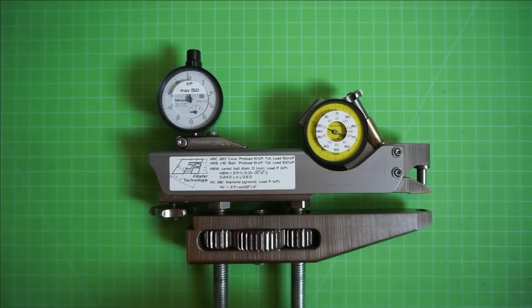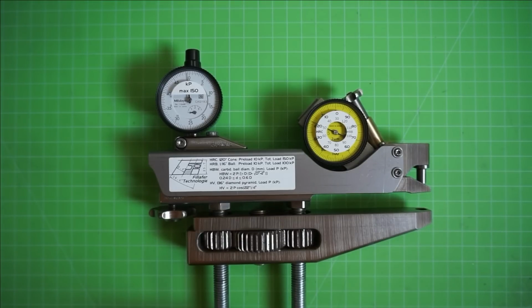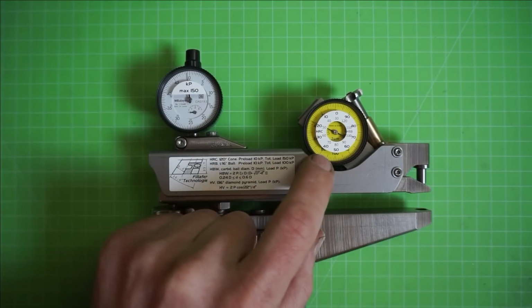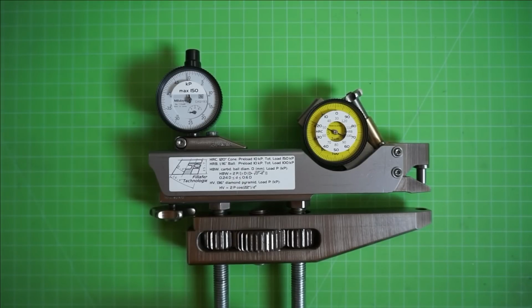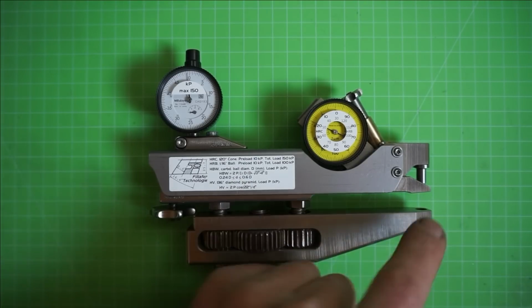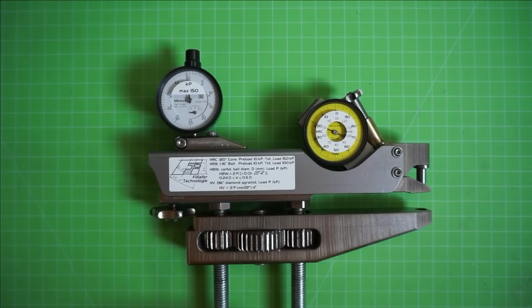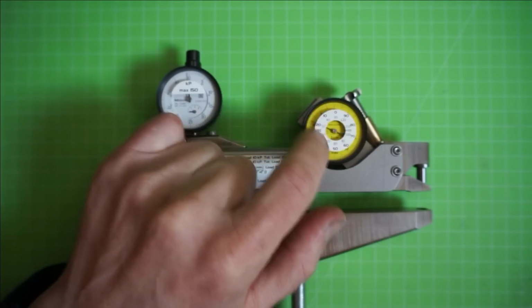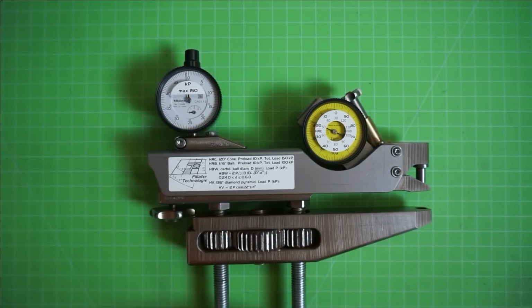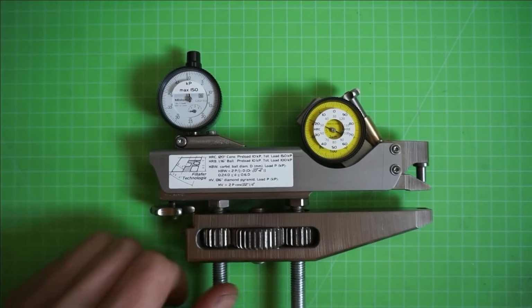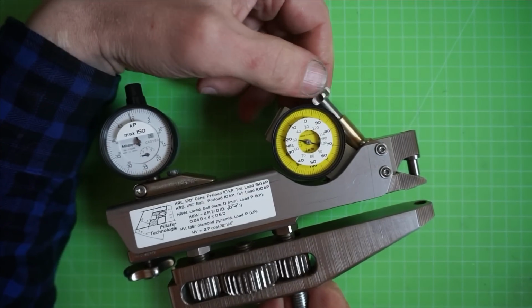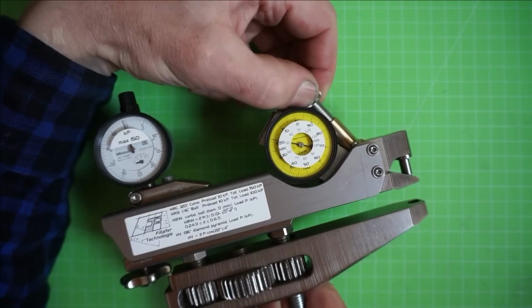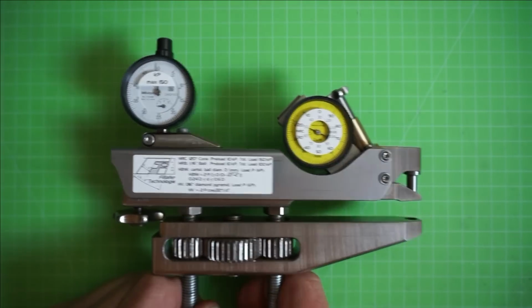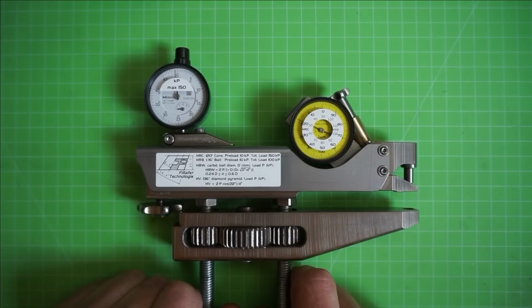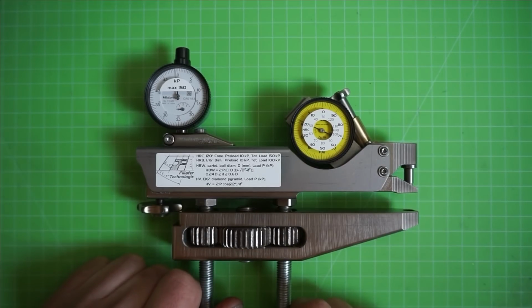So this allows us to force the indenter into the workpiece with a certain force. Then the second indicator here is used only for the Rockwell tests, and it measures how deep the indenter sinks into the surface. So this is also directly calibrated via this sticker ring here to directly read Rockwell cone and Rockwell ball units. And you zero this, I'll show it when we do the tests, with the aid of this thumb screw here, once the preload is applied. But I'll show that in a second. So essentially that's all that is to the tool.